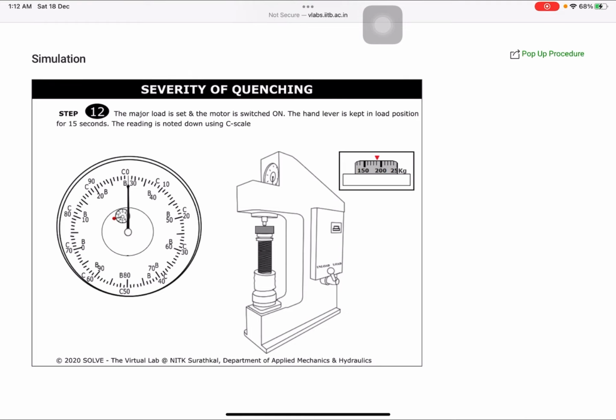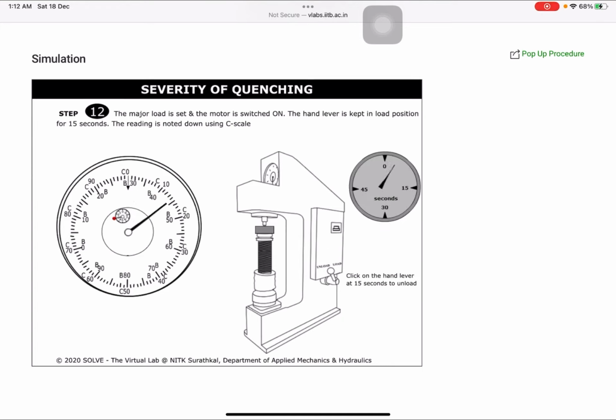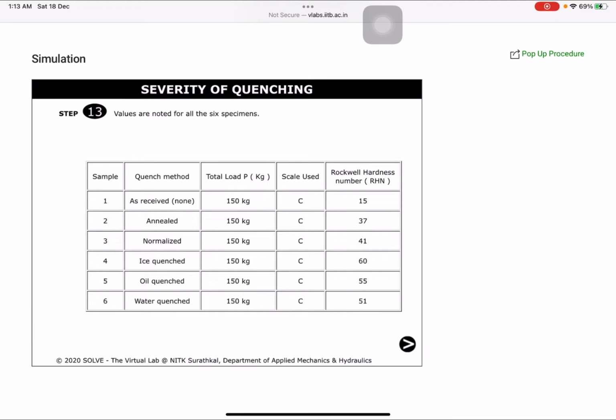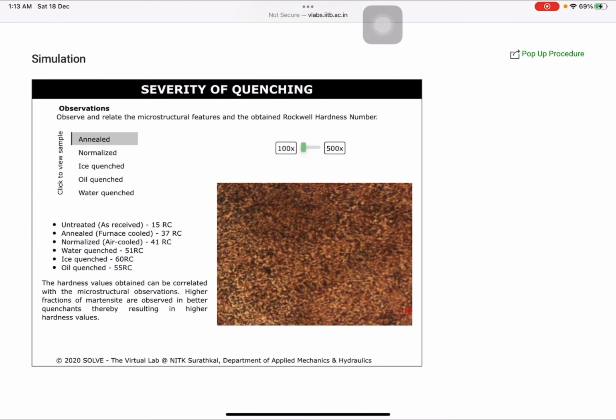Step ke-12, the major load is set and the motor is switched on. The hand lever is kept in load position for 15 seconds. The reading is noted down using C scale. Step ke-13, values are noted for all the 6 specimens. So the last part is observation. From this experiment, we can observe and relate the microstructural features and the obtained Rockwell hardness number.